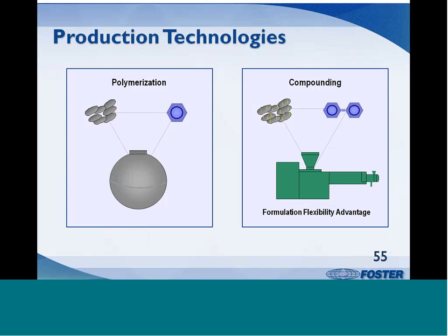There are 2 production routes to make a nanocomposite. In the first, untreated clay is added to a reactor, and the clay is exfoliated as the polymerization runs. With the extrusion compounding route, the treated clay is exposed to heat and shear in order to advance exfoliation. The compounding route has significant advantages in formulation flexibility. Nanoclay may be compounded with any combination of resins, fillers, and additives.